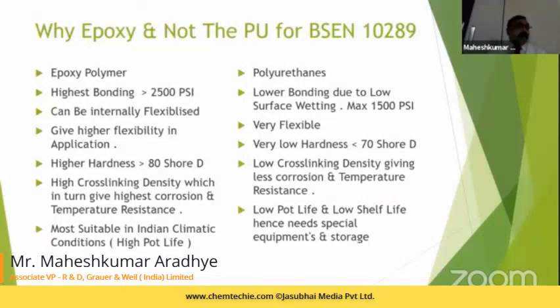So people ask why you are insisting on epoxies and not PU for BS EN 10289. The answer is that epoxies can give you the highest bonding, more than 2500 psi. It can be made internally flexibilized. You can modify epoxy and make it internally flexibilized. You can't modify polyurethanes and make them internally hard. No way. It's impossible to make polyurethane hard coatings that show a hardness of more than 70.